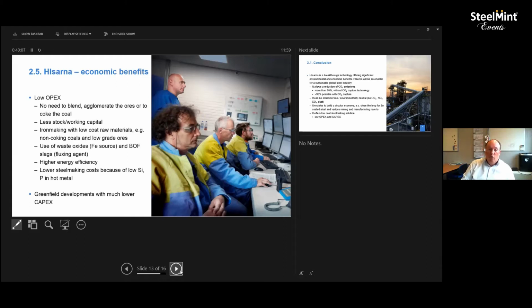We can easily use the sort of waste oxides and BOF slag, which we have already demonstrated. We've demonstrated the high energy efficiency. And because we produce a low silicon and low phosphorus hot metal, actually the cost in the BOF shop, in the LD shop, will be lower as well, because you do not need as much flux. That means you have a much lower slag volume. That means you have a much higher process yield. So that gives a lot of benefits.